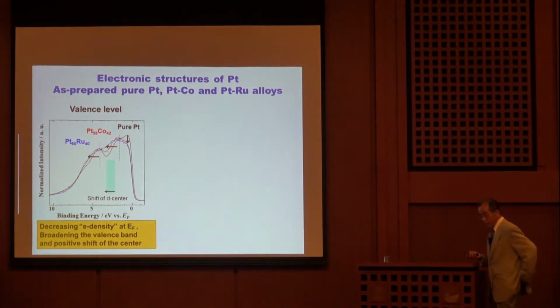And so next we try to examine the electronic structures of such a platinum skin surface. This shows the D-band structure change by alloying the platinum with cobalt or ruthenium. As you can see, the Fermi level area is a little bit changed, and the D-band center shifted to the higher energy direction, but it cannot be dealt with quantitatively.